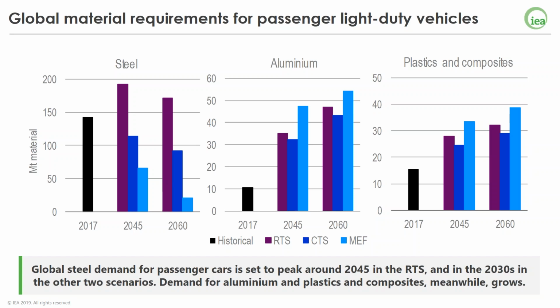A combination of that and more aggressive lightweighting, improved manufacturing yields, and increased reuse results in a considerable reduction in demand for steel, 50% lower than in the reference technology scenario in 2060. A moderate reduction in the demand for aluminum, 7% lower in 2060, and a 10% reduction in demand for plastics and composites. The greater push for lightweighting in the material efficiency variant results in a further decline in the demand for steel by an additional 3/4 in 2060 relative to the clean technology scenario, and an increase, because this is the material that's being shifted to, in aluminum, 1/4 in 2060 relative to the clean technology scenario, and also an increase in the plastics and composites demand by 1/3.